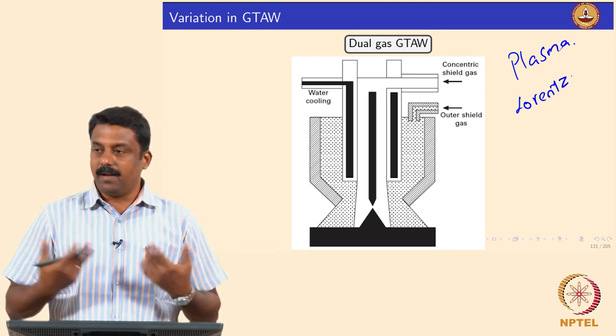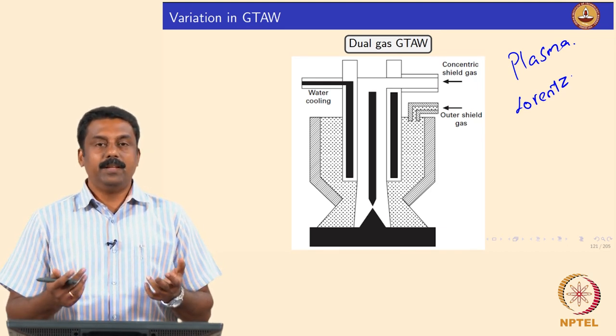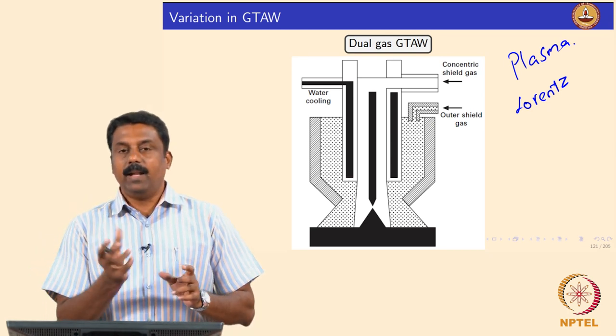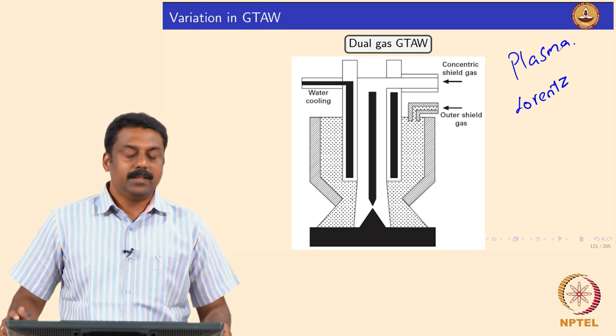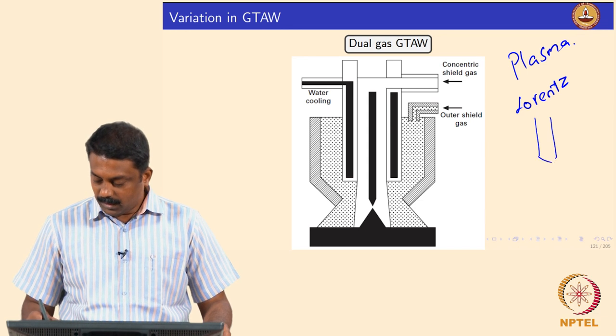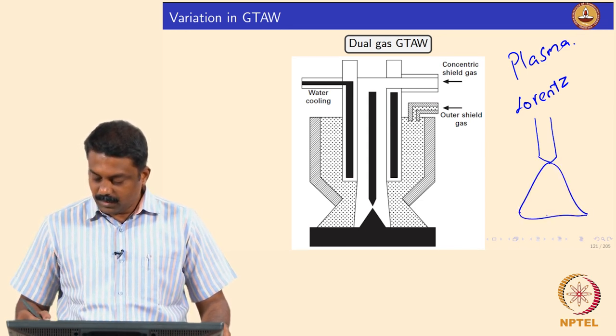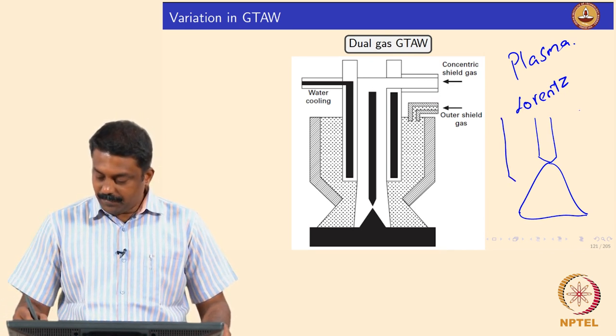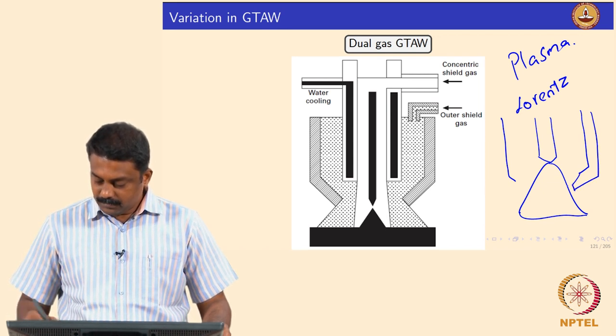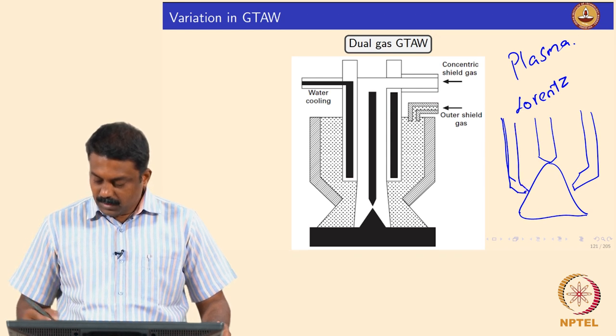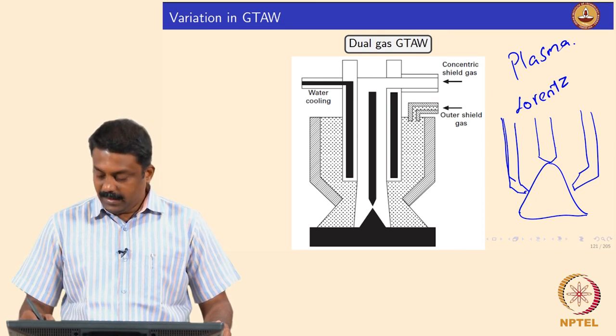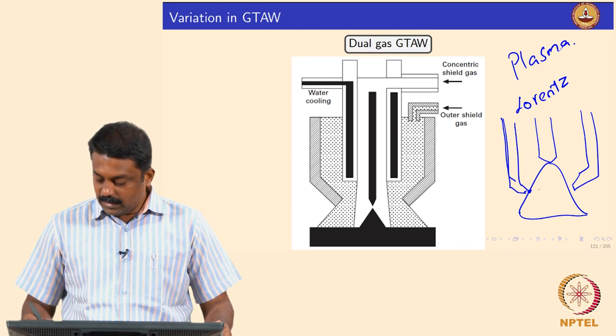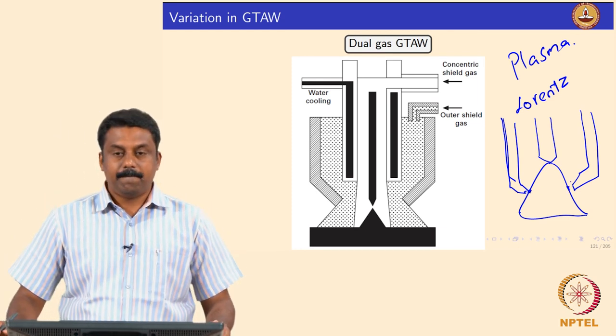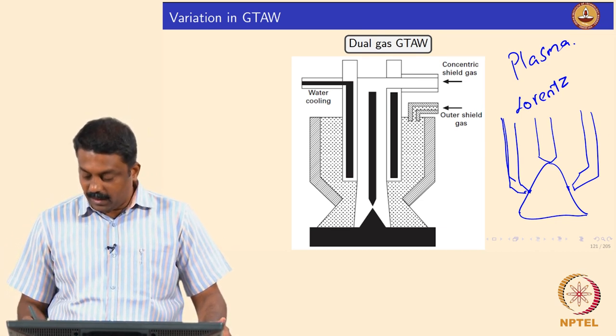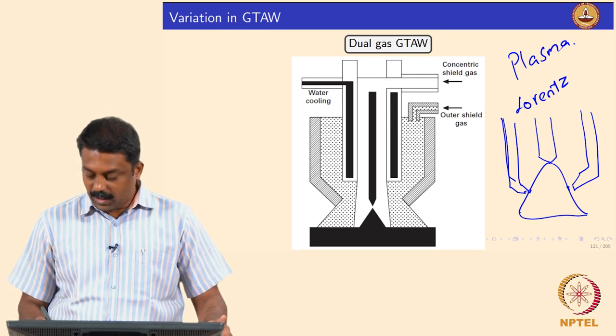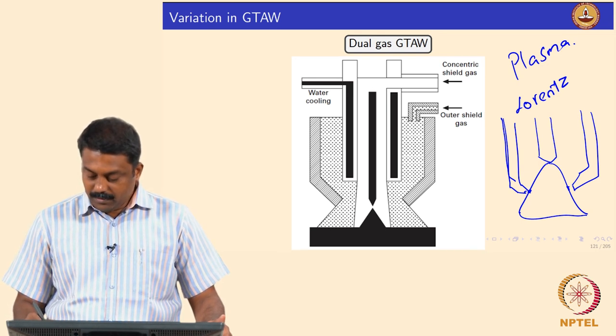You can pump up a lot of current, but that is not really practical. So simply what we can do is cool the arc envelope at a given location. For example, if you have a bell shaped arc formed, the trick is that we will have an additional gas coming at the halfway point between the electrode and base material when the arc is struck, and then we cool a certain area at the envelope of the arc. By doing so, we are constricting the arc, isn't it? So the arc envelope diameter decreases significantly, and locally we change the diameter of the arc.